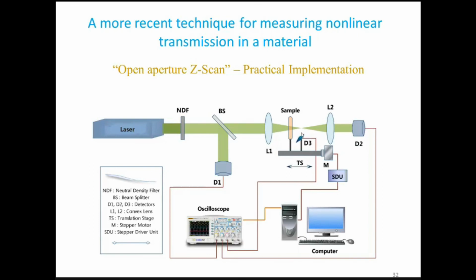The information that you are looking for in this experiment is how much the sample transmits when the intensity falling on it changes. So that is the information given to us by the Z-scan experiment. And there is a translation stage here to move the sample, and there are controllers. And usually in our lab, for instance, the experiment is automated because otherwise it will take a lot of time to make this measurement. Little by little you have to move and measure the transmission. So if you automate the experiment, it's much faster.